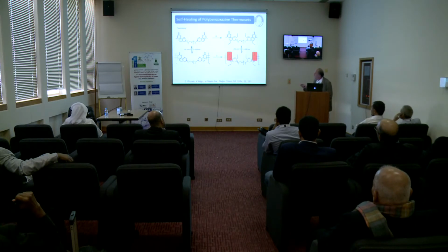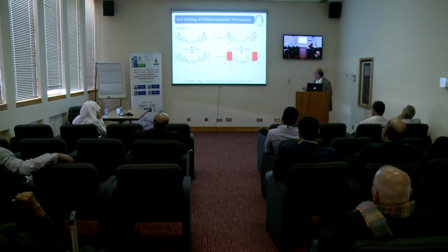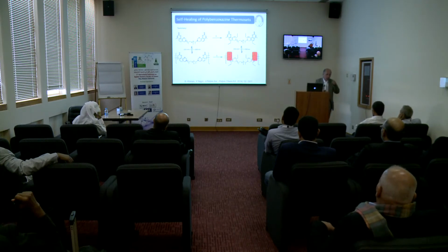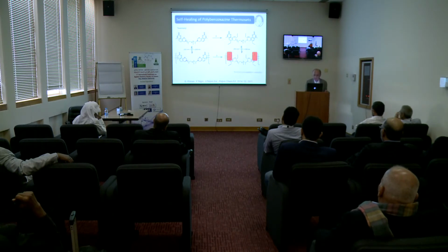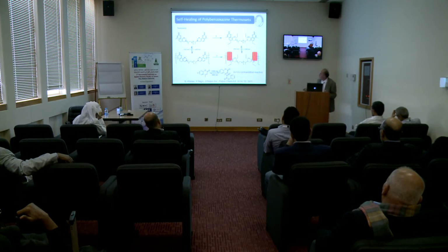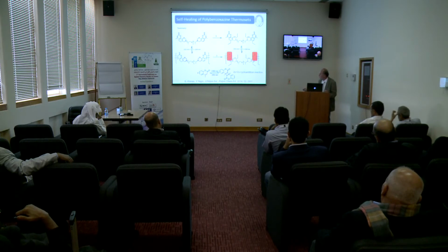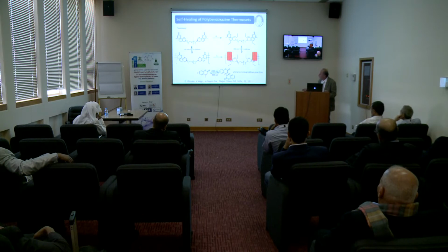First we heat it and this benzoxazine ring opens. We have coumarin groups in the network system. If you irradiate this above 300 nanometer, it will form a dimer. So if you cut a piece on the surface or something, irradiate this part by light, there will be self-healing. The damage will be unified again. Of course, this is a 2+2 cyclodimerization as we have presented here in the model molecule. Dimer is the initial one irradiated at 300 formed dimer. If you irradiate at lower wavelength, it goes back to original system.